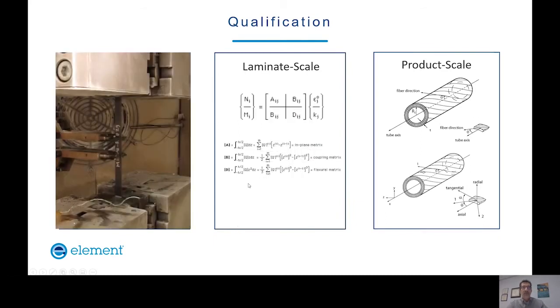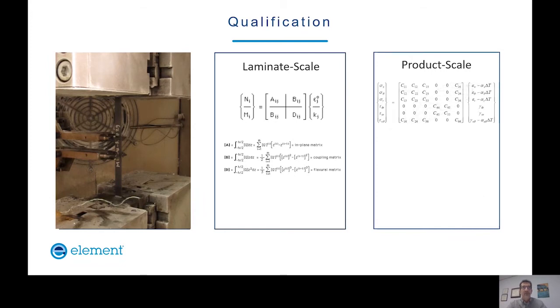As we look at what governs everything, on the laminate scale, we have what's traditionally called the ABD matrix. Here on the left-hand side, this can be thought of as a force that goes into the laminate. In the center, we have the stiffness matrix, the ABD, which can be thought of as a spring. And on the right-hand side, elongation or curvature that will occur in the product. On the product scale, very similar. We talk about stresses now in the product with the center matrix there consisting of C's. That's also going to be a stiffness component relative to the performance of the product.